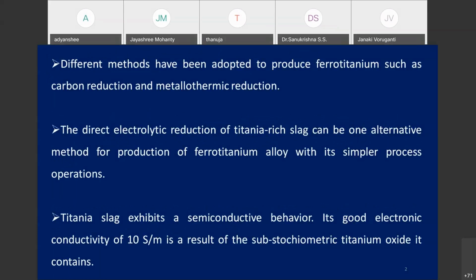or the titanium slag, mostly contains metal oxides. Ilmenite is FeTiO3, so it contains metal oxides. As we have already discussed in this process, you directly make the metal oxide into a compacted form and reduce it to metals. It is also found that not only a single metal oxide, but a mixture of metal oxides can also be used.